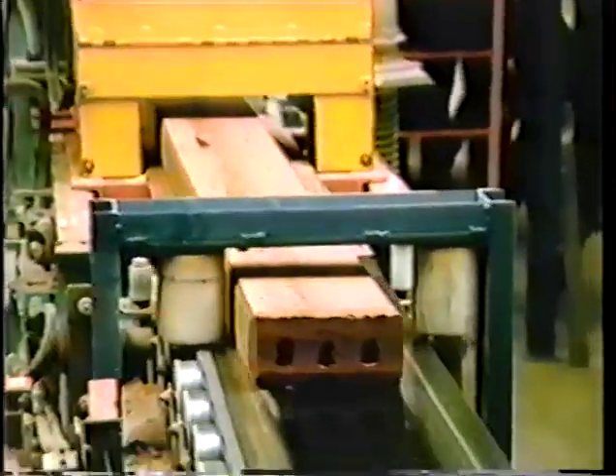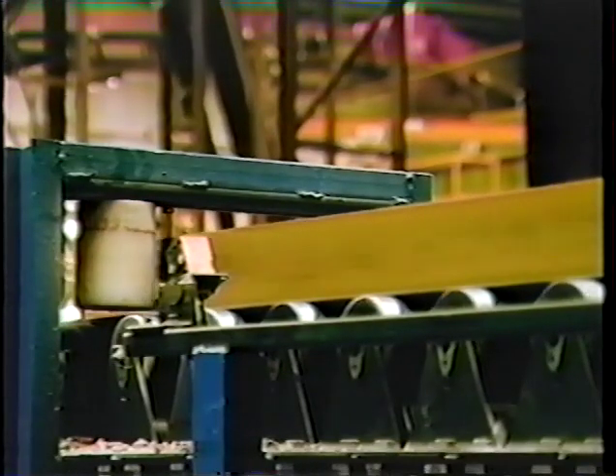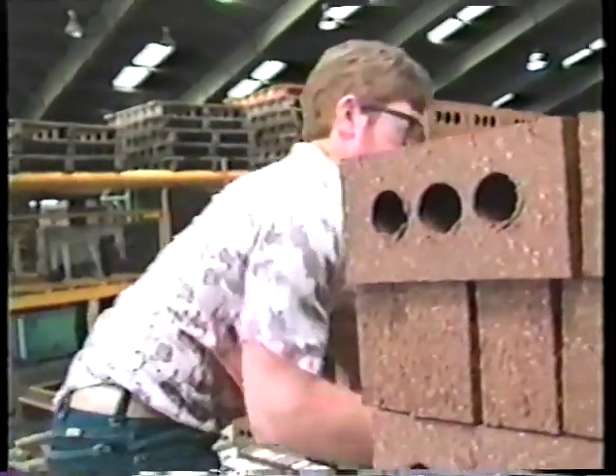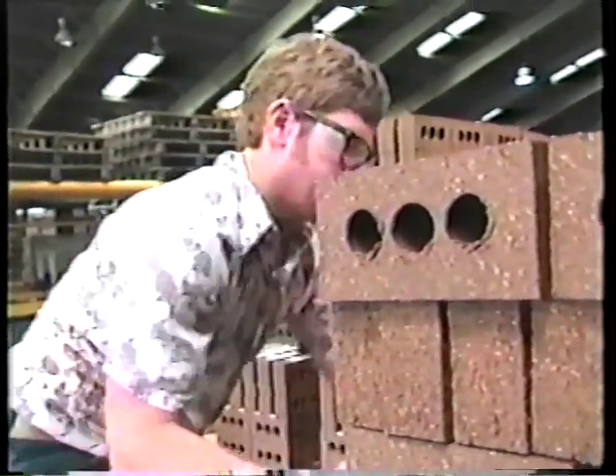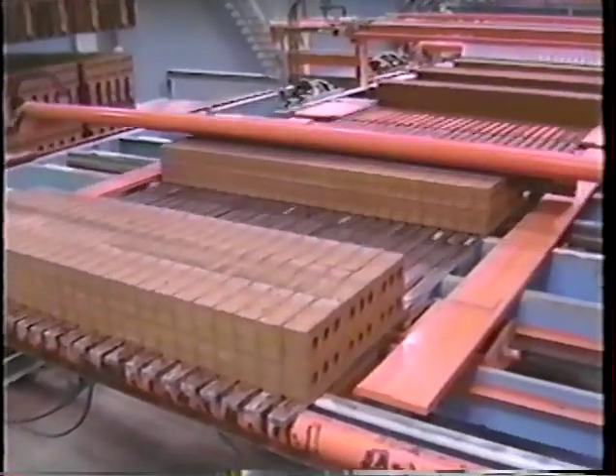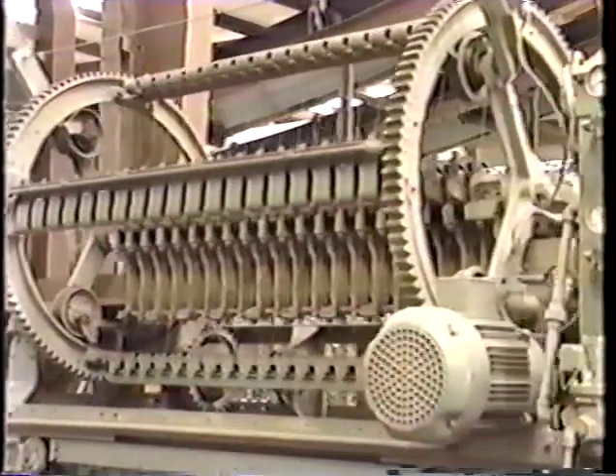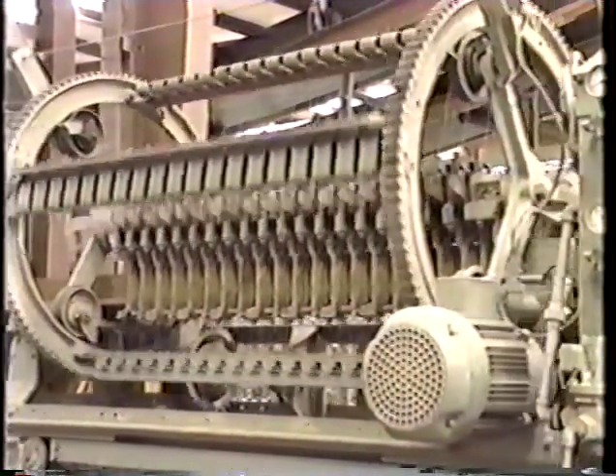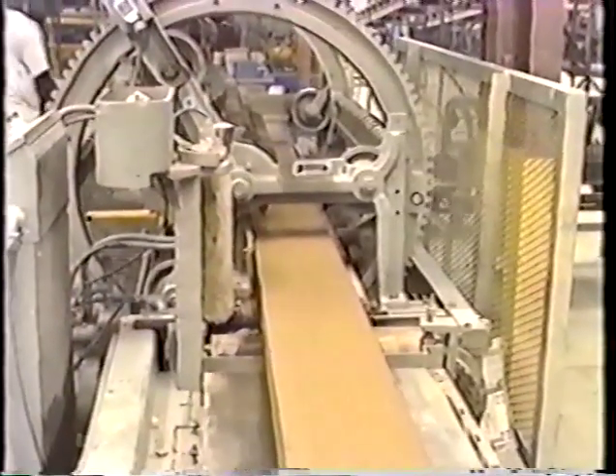The extrusion machinery can form brick whose core is not a solid continuous mass, but which has holes like these designed into it. Brick can be cored to save clay and fuel. But the primary reason is for stability and consistency of the drying and firing process, since heat will be allowed to get around the brick uniformly. It avoids a non-linear heat differential. Cracks won't be formed and the brick core and surface are thus optimized. The extruded clay is then cut by strong wires into individual green bricks.